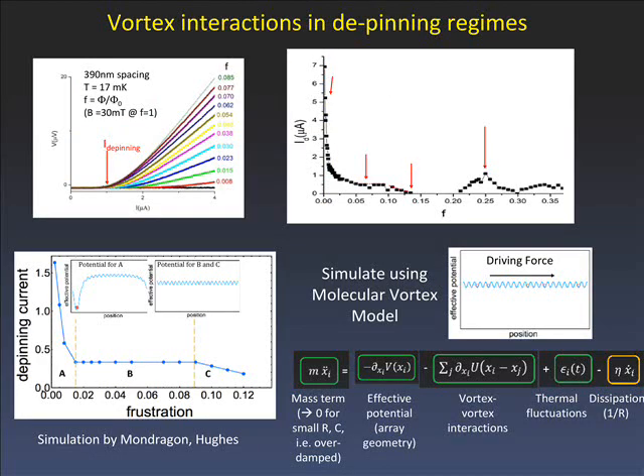Now we figure out the effects of vortex interactions in the depinning regimes by marking where we depin. You can see there's a transition from zero resistance to a linear resistance — the depinning current — and we plot this depinning current as a function of field. You can see various regimes: a sharp drop in depinning current, then it flattens out, drops to zero, and then goes up again. We're interested in understanding what these different regimes are and how they manifest in the dynamic behavior.